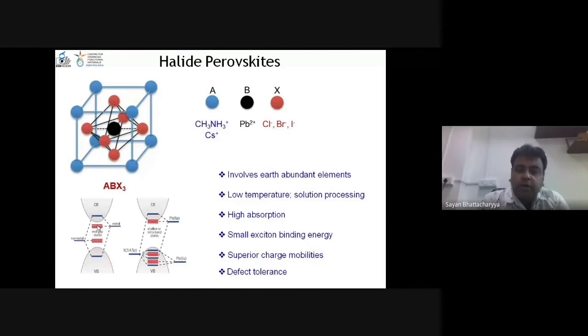Now there are various defects which come in. The defects create mid gap states here, so the transition can happen through this, which can slow down the process. So you basically get the defect band. In the case of the perovskites, why it is so good is that the defect bands mostly lie at the bottom of the conduction band. So they do not interfere with the absorption or the emission process at all.